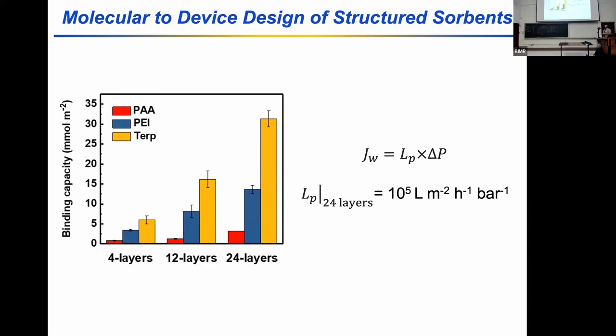And that's what we're showing in the left here. The most important thing is that as we change the number of layers, you see a corresponding change in the saturated amount of copper captured, right? So the capture capacity of the 12-layer terpyridine membrane is about 3 times higher than that of the 4-layer. And the 24-layer is about 2 times higher than the 12-layer, which means that all of the binding sites are accessible. And we've got pretty large permeabilities for those that care about this type of thing. The hydraulic permeability of the 24-layer membrane is about 100,000 LMH per bar, so pretty notable.